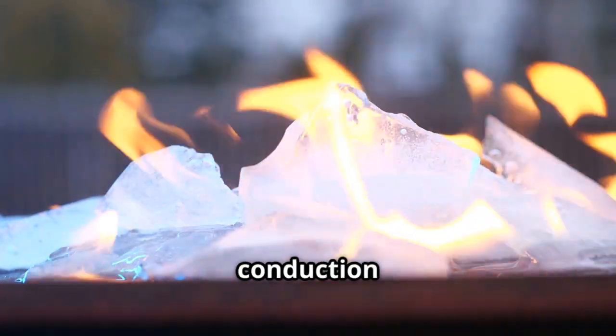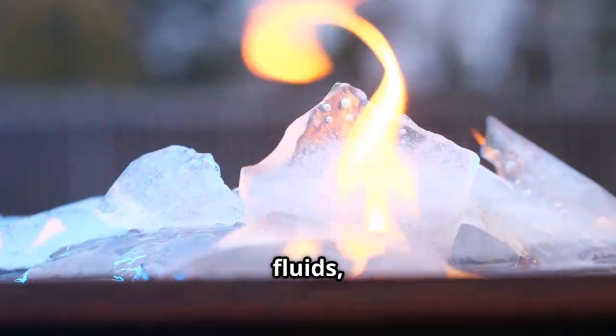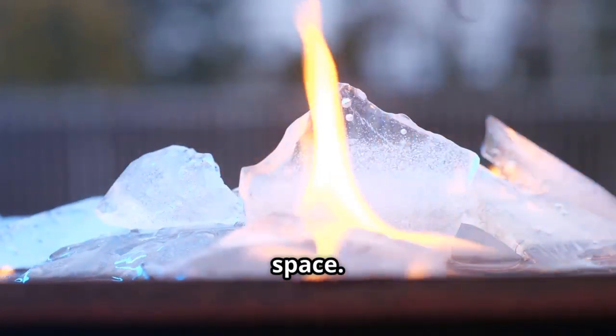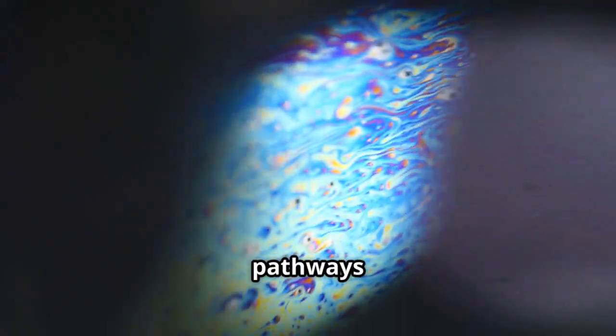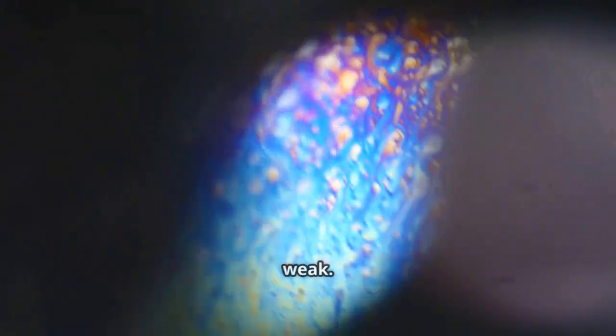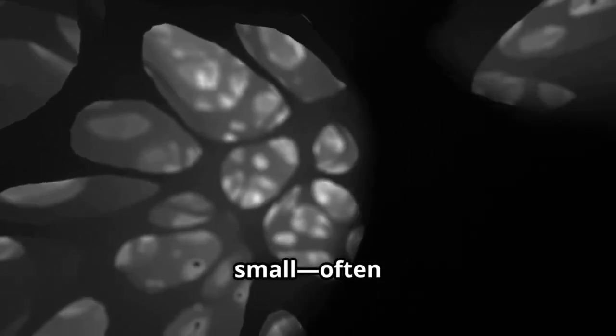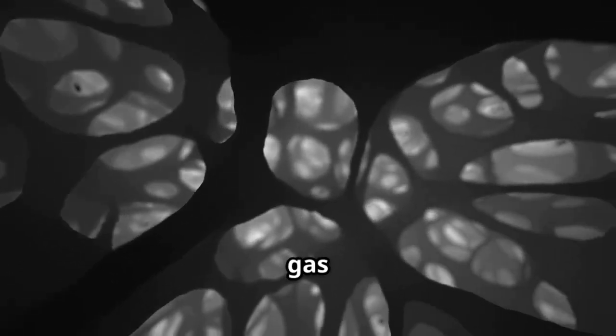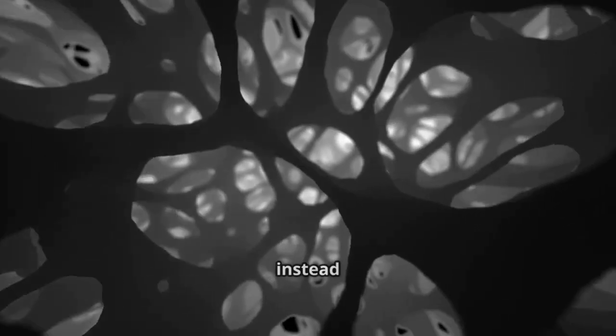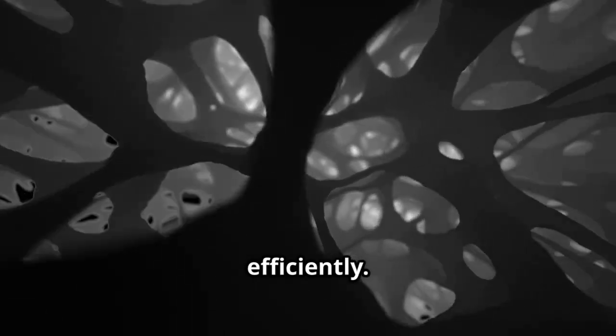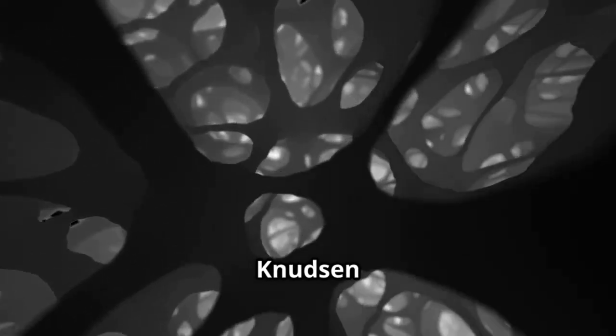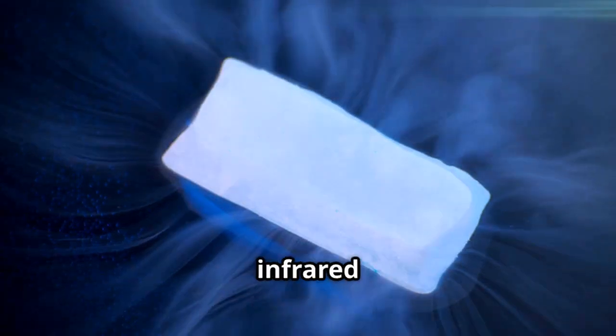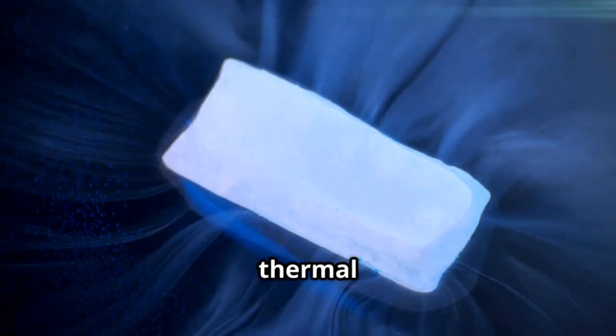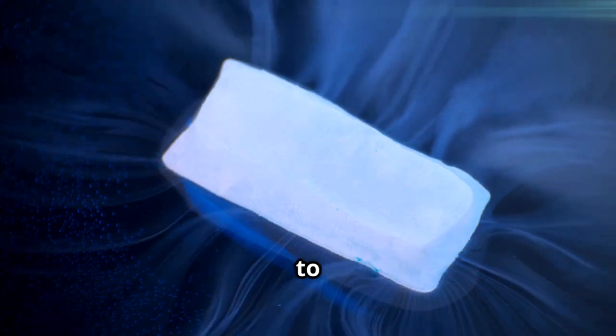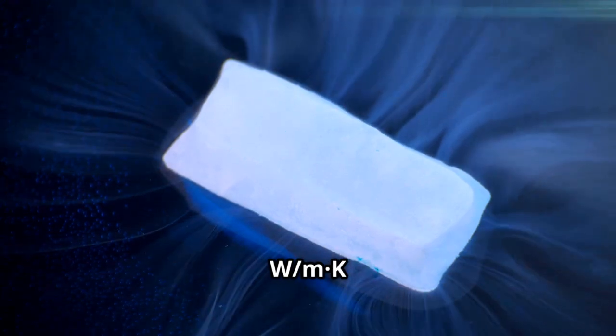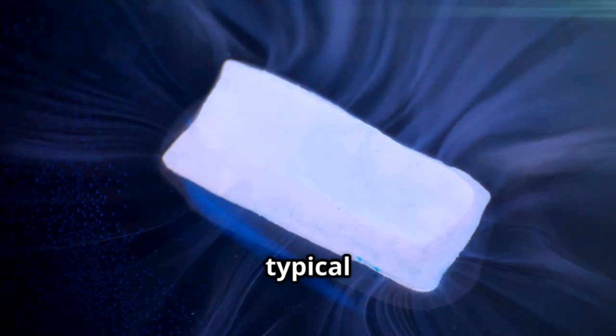Heat normally moves by conduction through solids, convection in fluids, and radiation through empty space. In aerogel, the solid pathways are extremely thin, so conduction is weak. The pores are so small, often tens of nanometers, that gas molecules keep bouncing into the pore walls instead of carrying heat efficiently. This suppression of gas conduction is the Knudsen effect. Combine that with tuned infrared opacity, and you get very low thermal conductivity, often 0.013 to 0.02 W/mK at room conditions, far below typical foams.